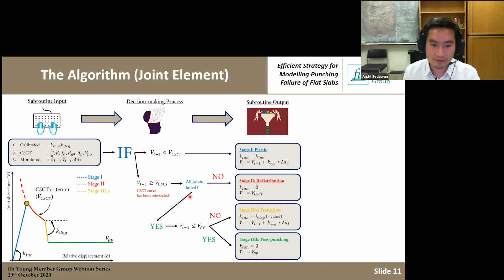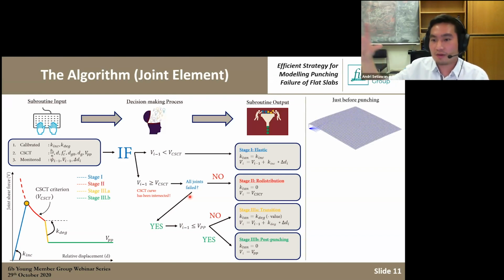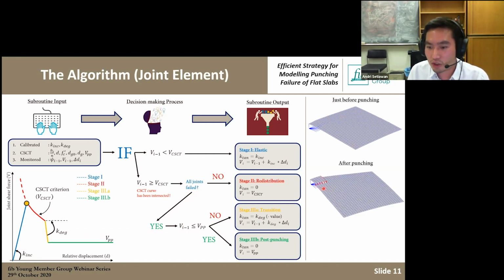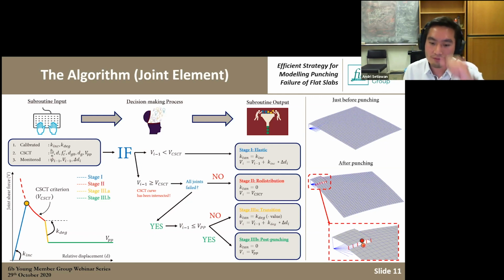So by having the constitutive behavior that consists of stage 1, stage 2, stage 3, A and B, we are trying to simulate all the important milestones of the punching phenomenon in slabs. This is the physical illustration. Just before punching, you can still see that the slabs are intact between the inner and the outer part. But just after punching, if we zoom into this region, the red dots and the yellow dots represent the first and the second nodes that have started to separate because the punching failure has been triggered there. So this is how the model will simulate the physical failure here.